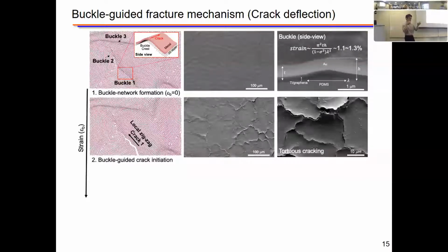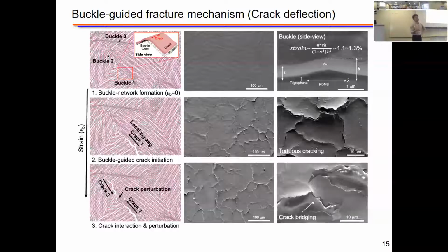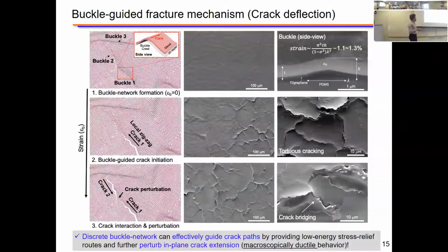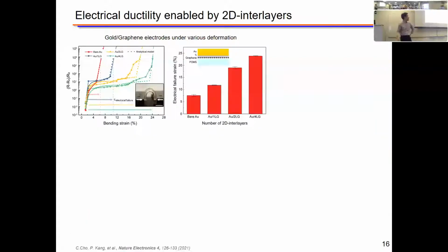Cracks preferentially initiate at the crests of the buckles and propagate along the heterogeneous network, resulting in this tortuous cracking behavior. Multiple cracks interact and intersect each other, effectively delaying the complete disconnection of the metal film. We also observe multiple spots of crack-bridging areas that contribute to forming an effective conductive path through the fracture surface. So we deduce that this discrete buckle network can effectively guide crack paths and perturb in-plane crack extension, resulting in macroscopically ductile behavior.